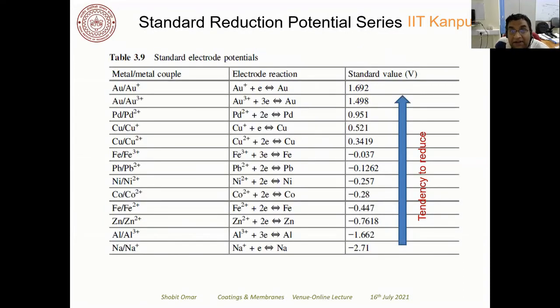And if you look at the standard reduction potential series, there are a lot of elements there, and also standard values with respect to SHE. You see that gold has a higher potential. Gold ions, when they get reduced to gold, have a higher potential compared to something like copper ions, which get reduced to copper. So the higher this value, the higher the tendency of the ion to get reduced.